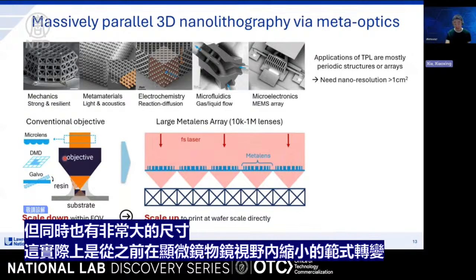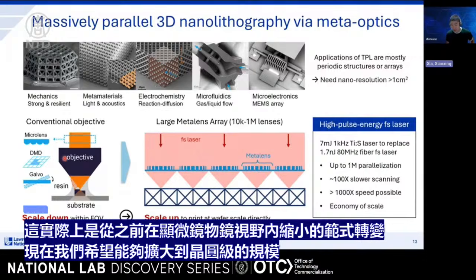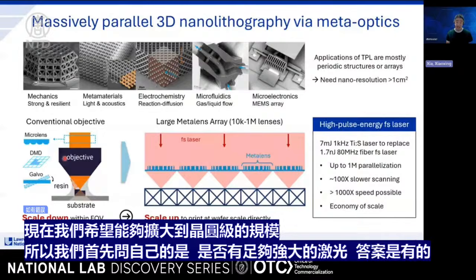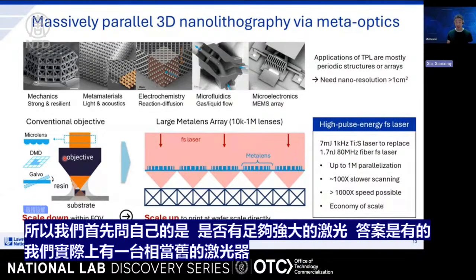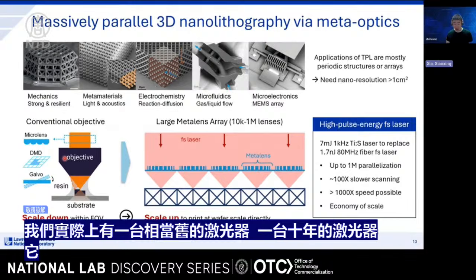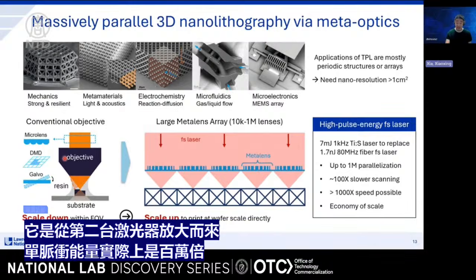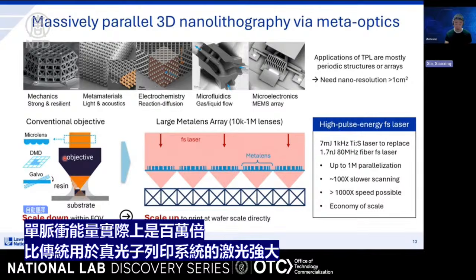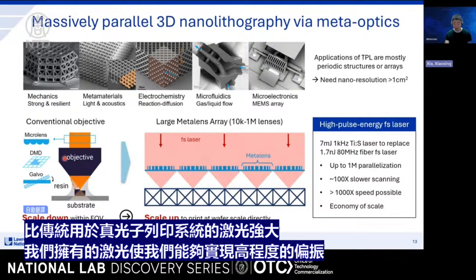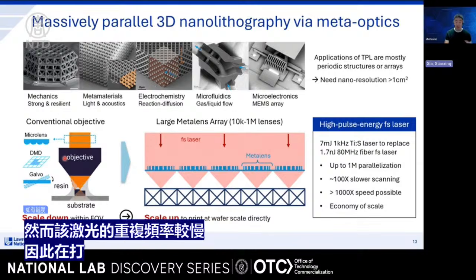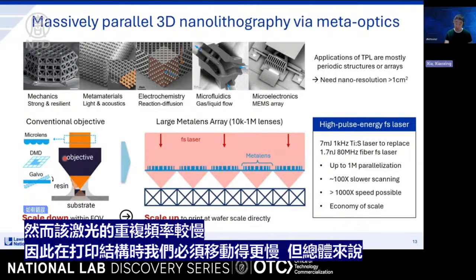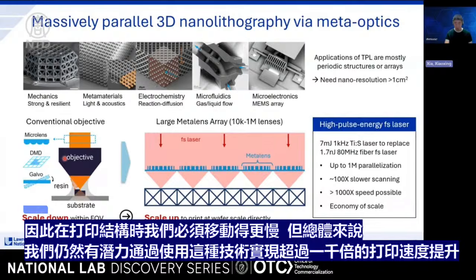So the first question we ask ourselves is, is there a laser that is powerful enough? The answer is yes. We actually have a pretty old laser, a 10 year old amplified femtosecond laser. Individual pulse energy is actually 1 million times stronger than the traditional laser used in two-photon printing systems. So we have a laser that enables us to achieve large degree parallelization. However, the repetition rate of that laser is slower, so we have to move slower when we print 3D structures. But overall, we can still have the potential to have more than 1,000 times printing speed enhancement by using this parallelization scheme.